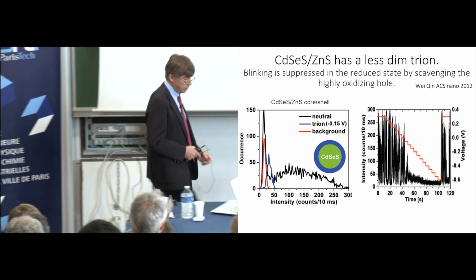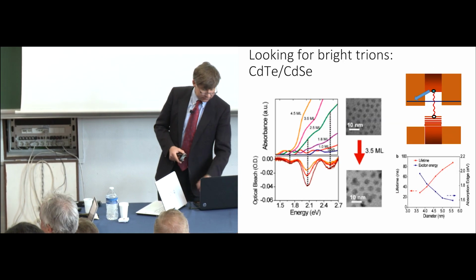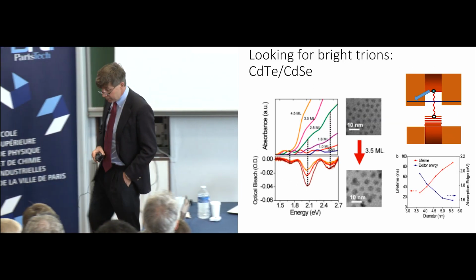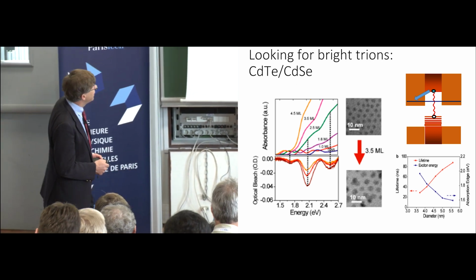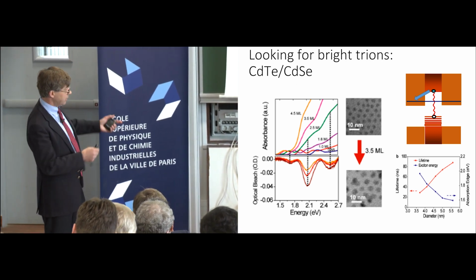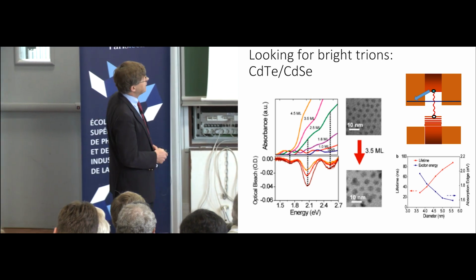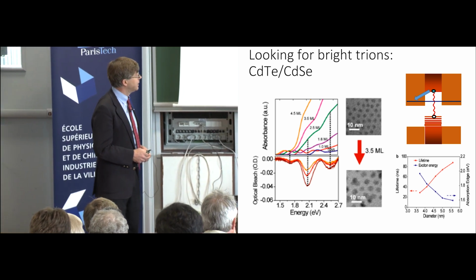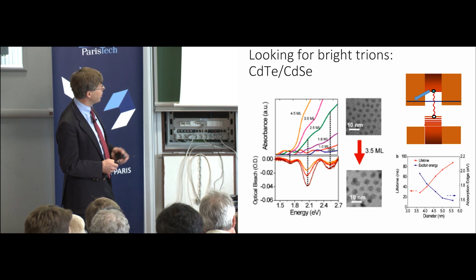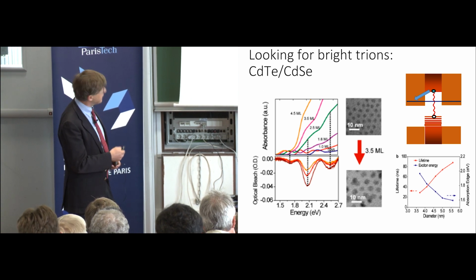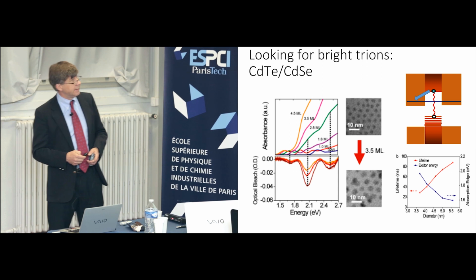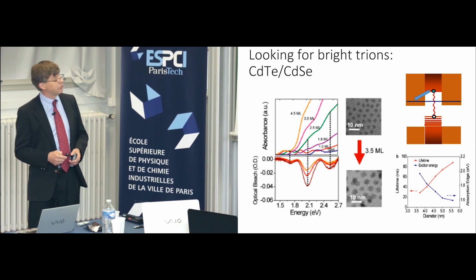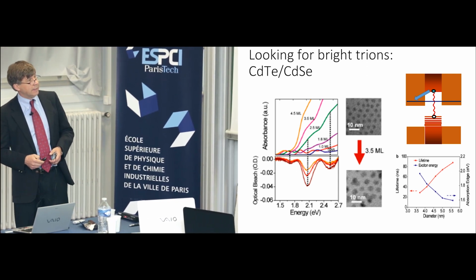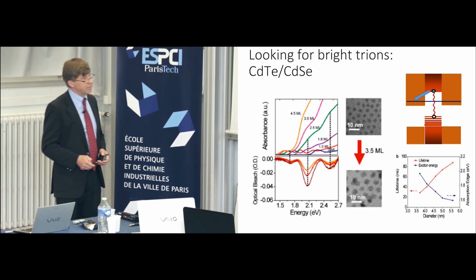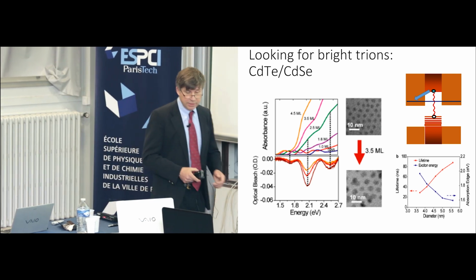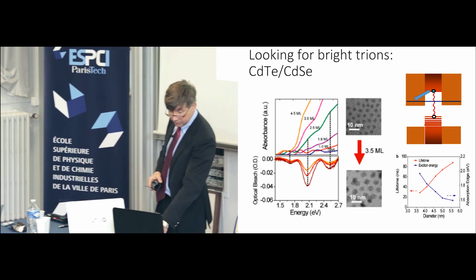And what we're looking for was a bright, charged, small dot at room temperature. So we started looking into the type 2 core-shell structures, where in principle the electron and the hole are separated so that the Auger process, in this simple interpretation, would be reduced or eliminated. And so we looked at this cadmium telluride, cadmium selenide, did the synthesis, see the huge Stokes shift. This was not new. Saw the lengthening of the radiative lifetime. Everything matched. And then we looked for the trion of those.